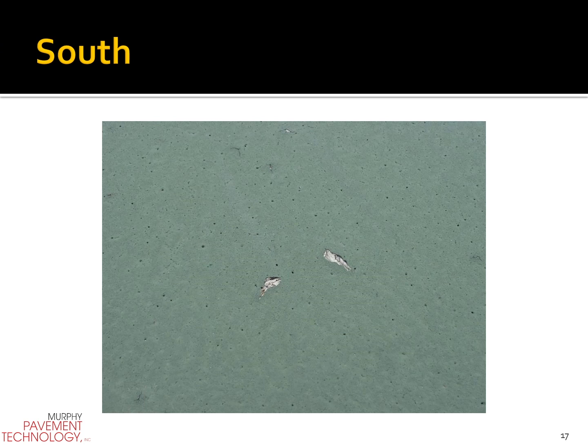This is just an example of crushing aggregate. The thickness wasn't adequate, and a tennis court coating started to fall off within about 6 months, and it really just came down to crushing the coarse aggregate particles. This can be avoided with the proper lift thickness.